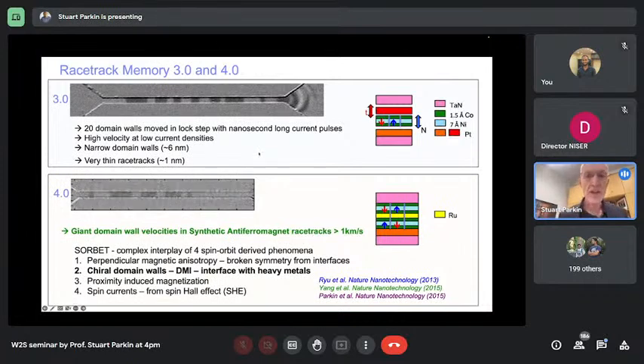So it turns out when we went to the top material, there's just a racetrack consisting of cobalt, nickel, cobalt. To the bottom, this is the synthetic antiferromagnet. Now we have two cobalt, nickel, cobalt layers separated by this yellow layer of ruthenium. And as you can see in this cartoon, these layers are coupled anti-parallel to one another.